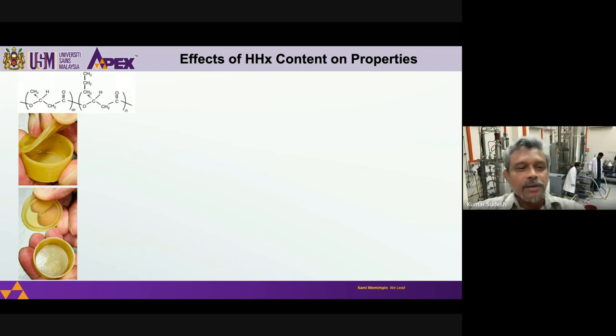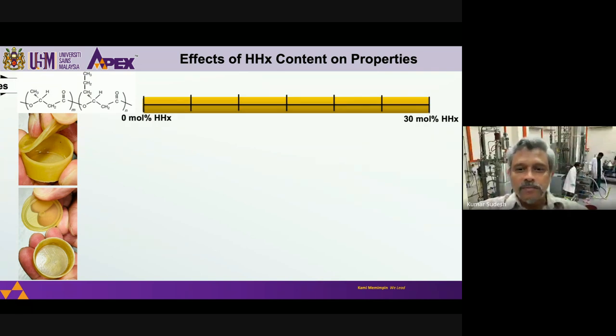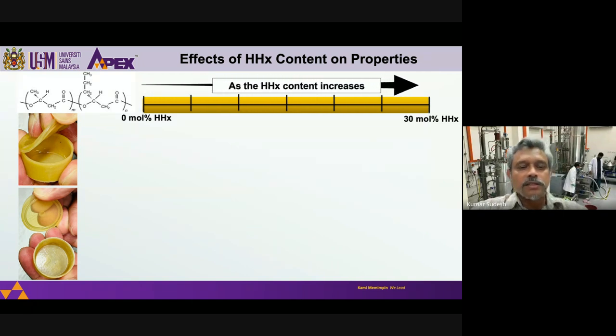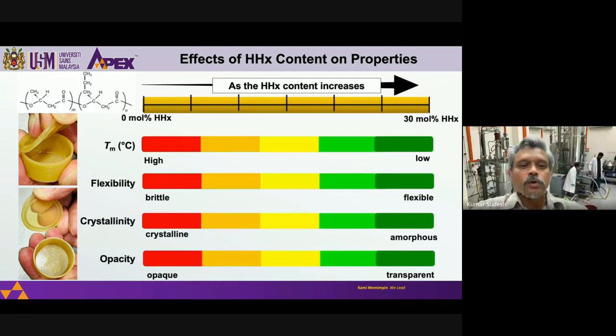So now, please let me know if my time is up, I can introduce to you a little bit about the type of properties that you can get by controlling the monomer composition. If you still remember just now, I showed that the type of PHA that we are producing now contains two different monomers. The smaller one, which is 4 carbon, is called 3-hydroxybutyrate, and the one on the right is 6 carbon, which is 3-hydroxyhexanoate. So by controlling the ratio of these two monomers, we can control the properties of the PHA. For example, when we increase the HHX fraction from 0 to 30 mole %, we can control all these properties.